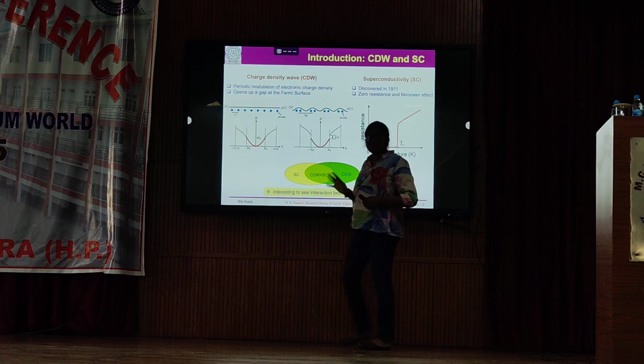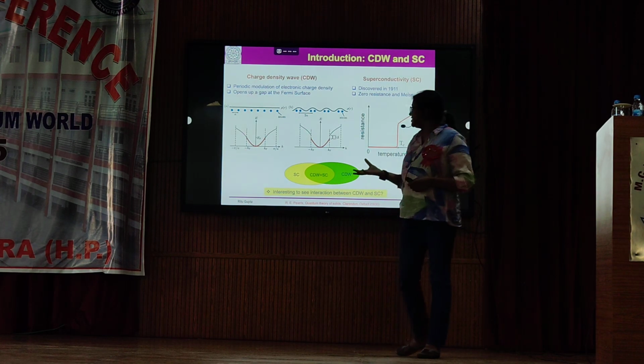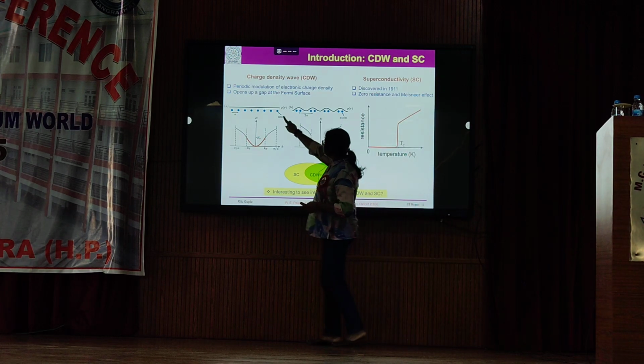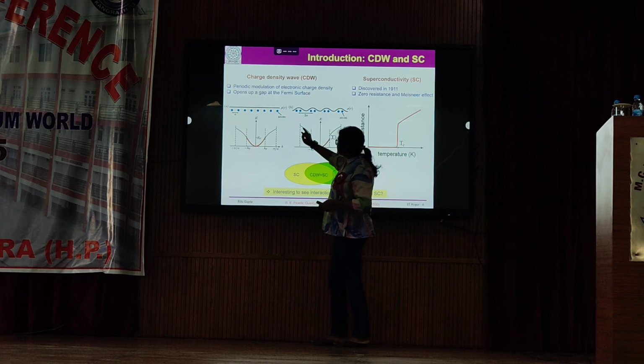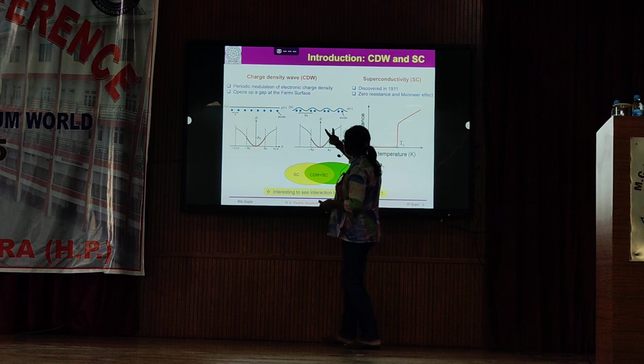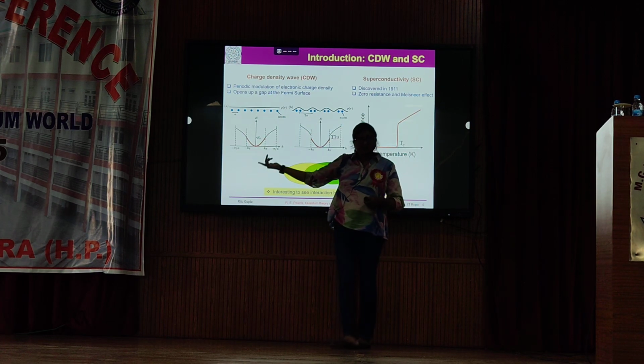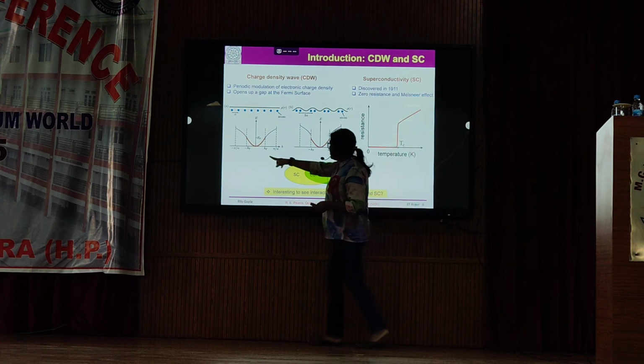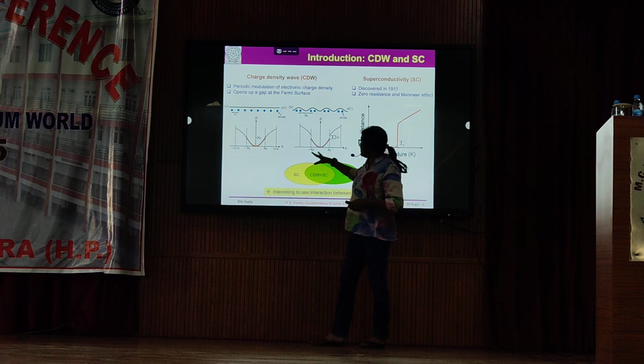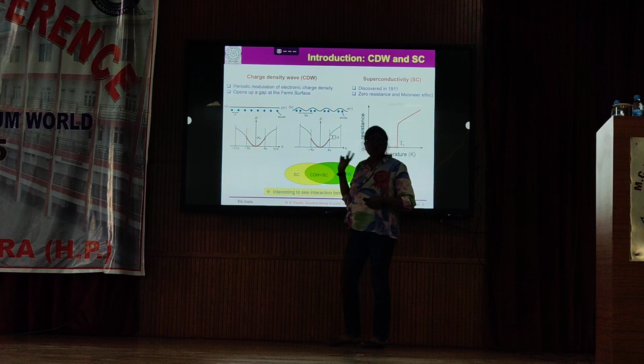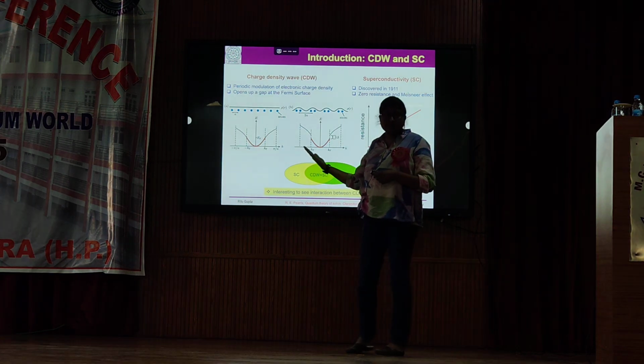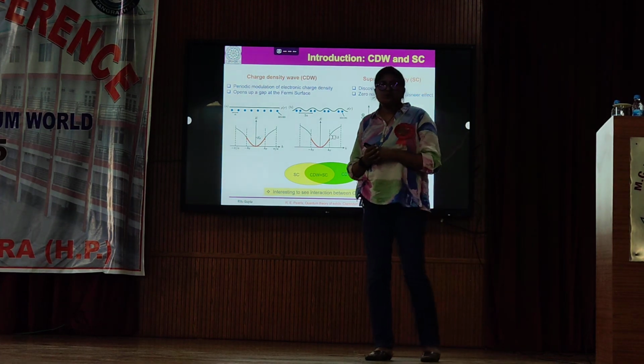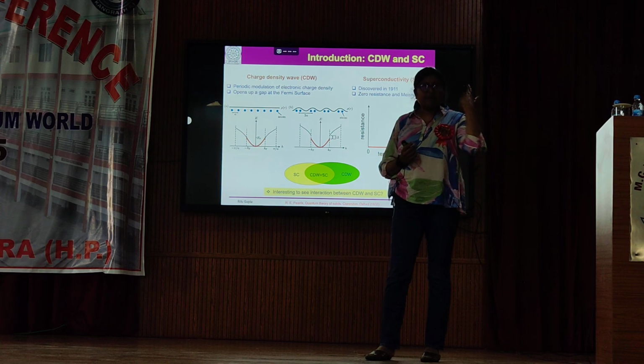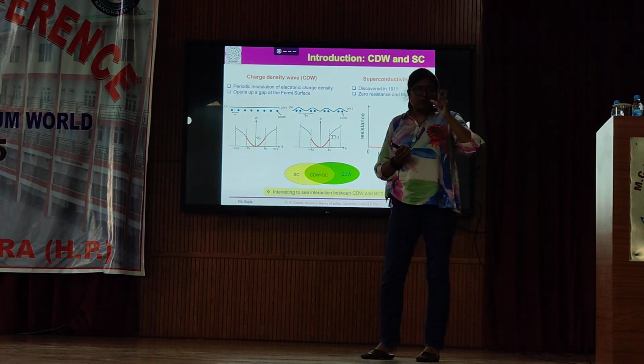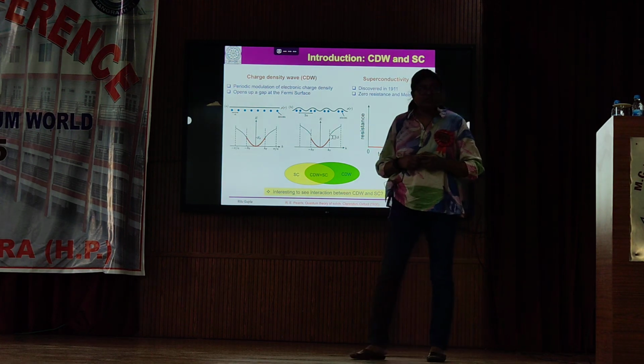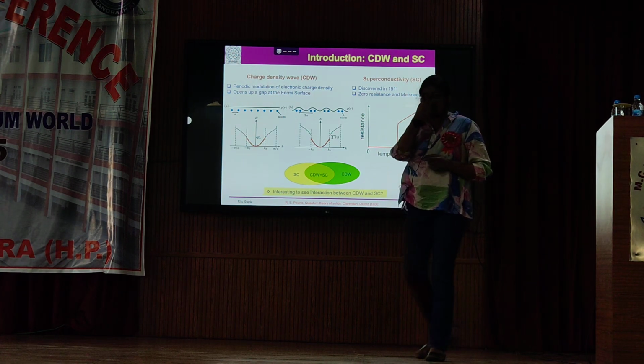But what happens below a certain temperature is that the lattice modulates itself. Now the atoms are not equispaced, but they form pairs like this. Before, the spacing was a, but now it becomes 2a. So there will be new Brillouin zone boundaries at minus pi by 2a and plus pi by 2a. Those Brillouin zone boundaries will now lie inside the occupied electronic states, and we all know what happens at the Brillouin zone boundary. If a wave is coming, it is reflected back and gives you a stationary wave, right? So there is an opening of the gap at the Brillouin zone boundary. This is what is happening whenever you have a charge density wave in your system.